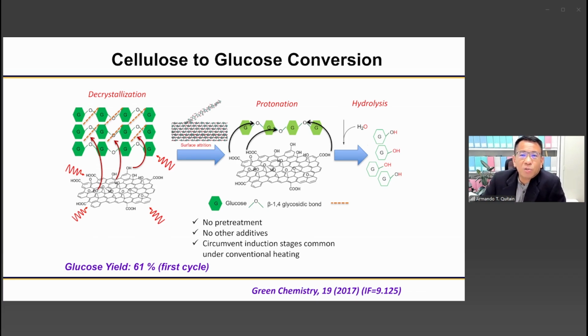Okay, so now for cellulose to glucose conversion, as I've mentioned, we can achieve this by hydrolysis. And normally this will require a very high temperature of 400 degrees centigrade using only water. But that will require very high pressure as well, other than high temperature. So as much as possible, we would like to lower the operating conditions. In our case, using microwave and carbon synergy, we were able to lower the temperature to about 200 degrees centigrade and getting glucose yield of 61% in the first cycle.